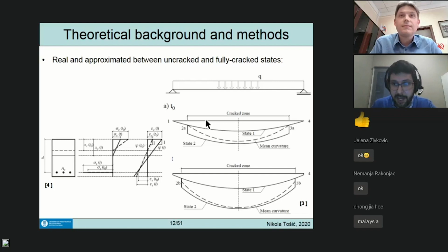What happens over time is that the effects of creep and shrinkage further increase this curvature. Why? Because they increase the strain in concrete. So looking at the cross section, you start from a concrete strain, epsilon c at T0, with this neutral axis here and this cross section strain line.